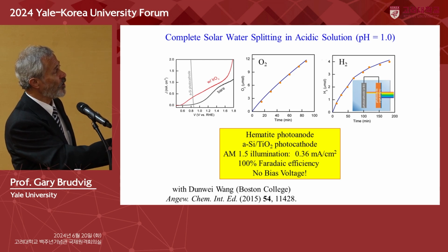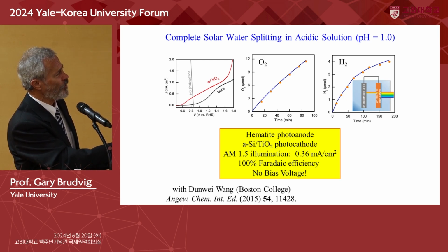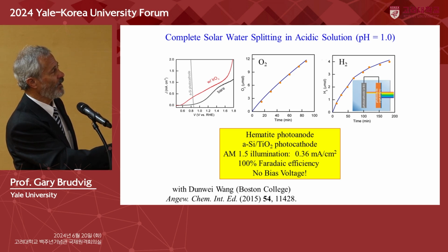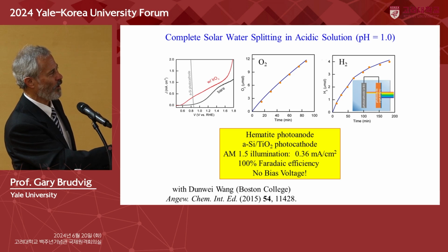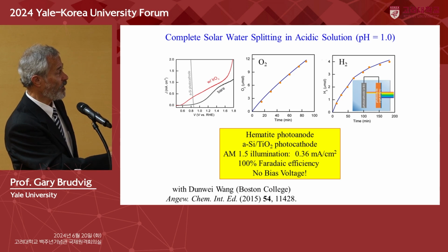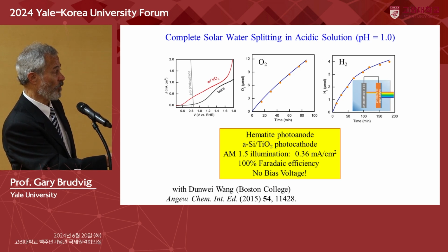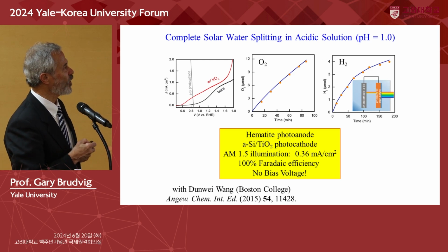And this is a system where, within a single chamber, we utilize an iridium catalyst on the photoanode and an amorphous silicon photocathode. And this is the idea. We have a photoanode that absorbs the blue and the shorter wavelength range of the visible photons. The longer wavelength photons pass through and drive the photocathode. And we get overall water splitting with 100% Faraday efficiency and no applied voltage. So it's just a complete water splitting cell.